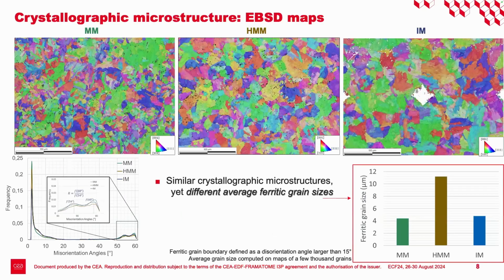As regards the crystallographic microstructure, EBSD maps have been performed, and here is plotted the probability density function of misorientation angles for the three materials. And you can see that you have almost exactly the same curve for the three materials, which is representative of a bainitic microstructure. But what is interesting here is that if you define an area inside which you don't have more than 15 degrees misorientation angle as being a ferritic grain, then you can observe that the homogenized model material has a much larger grain size than the two others.